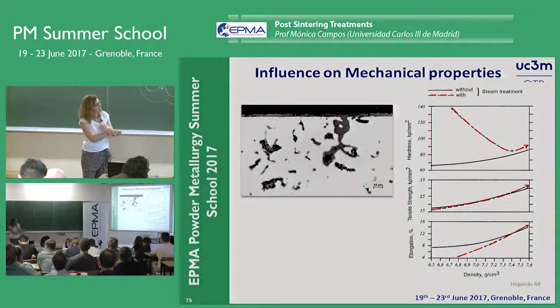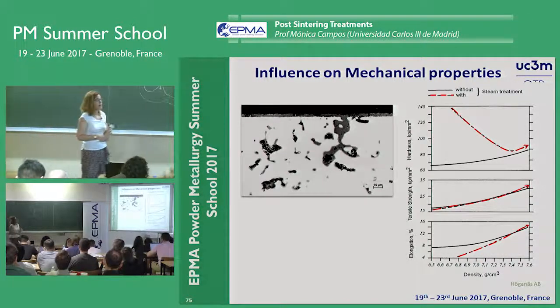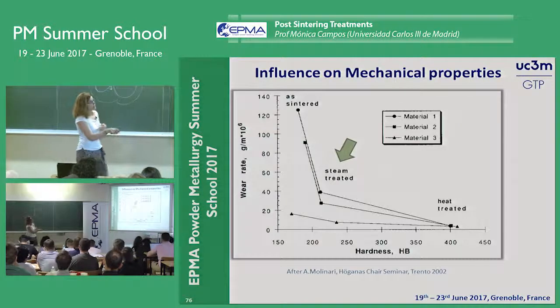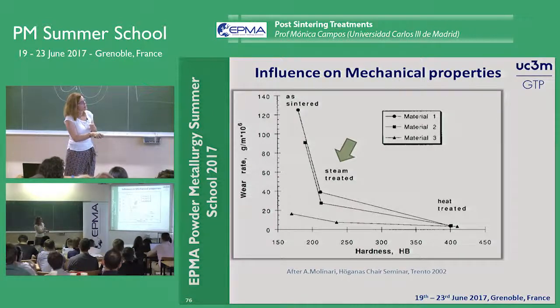Look here, this is the coating, the oxide layer, and how the open porosity is also covered by this very well adhered oxide layer. It works very nicely if we are thinking of wear resistance. This is the wear rate of the sintered component and the steam treated component.